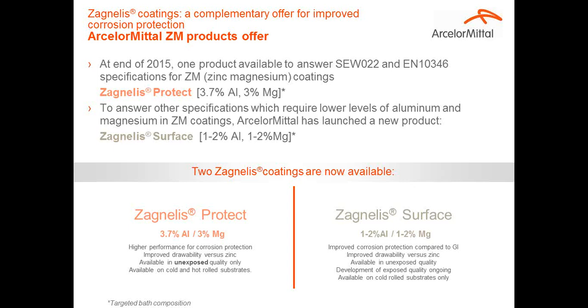But to answer other specifications requiring lower amounts of aluminum and magnesium, ArcelorMittal has developed a new product called Zagnelis Surface. This product will contain between 1 and 2% of aluminum and 1 and 2% of magnesium. It will bring an improved corrosion protection compared to pure zinc coating. We also have a good durability of the coating. It is already available in unexposed quality and will be available in the coming weeks in exposed quality. This coating will be available for cold rolled substrates.